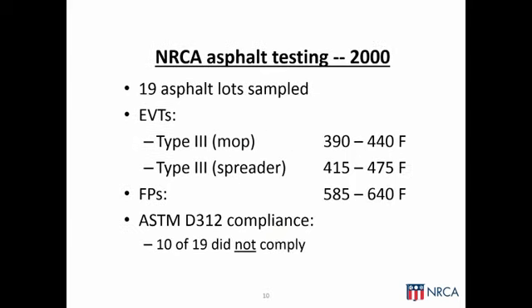NRCA did similar testing in 2000. This particular year, we tested 19 different lots of asphalt. And you'll notice the EVTs between 2000 and 10 years previous stayed substantially the same. A little bit of change in values, 5 or 10 degrees, but nothing significant. I do want to point out to you, though, something that was surprising to us in the 2000 study was the elevated temperature of asphalt's flashpoints. At this point in time, the ASTM standard for asphalt was calling for a minimum flash point of 500 degrees Fahrenheit, and we were comfortable that most manufacturers were meeting that.